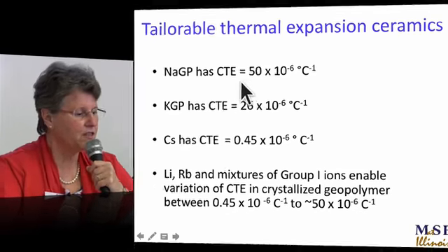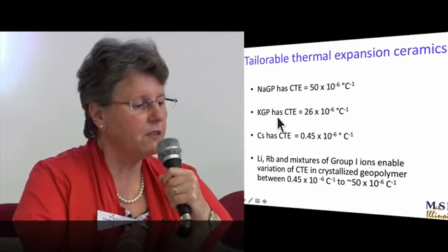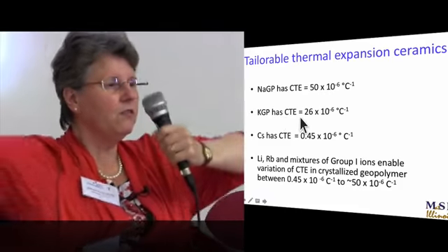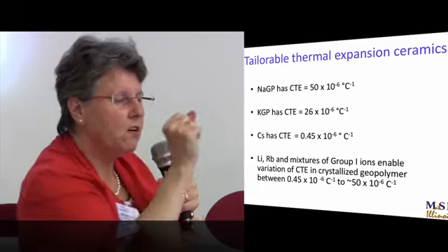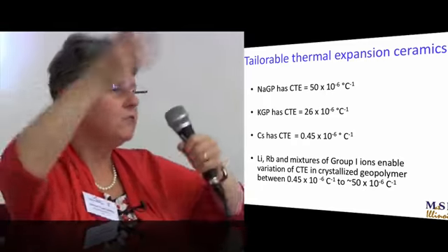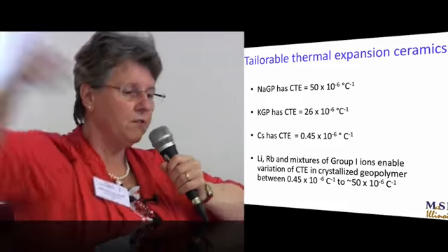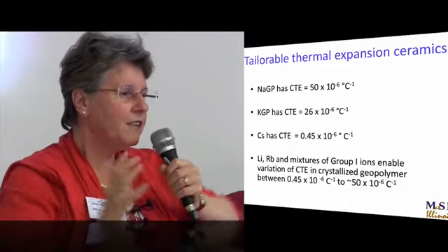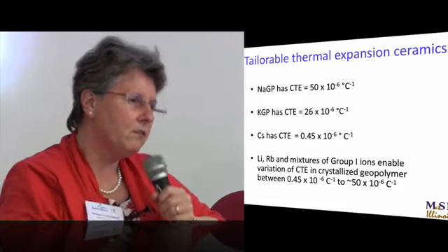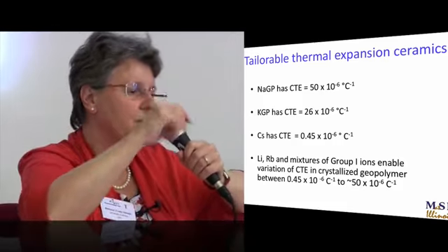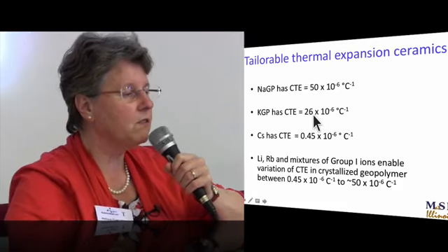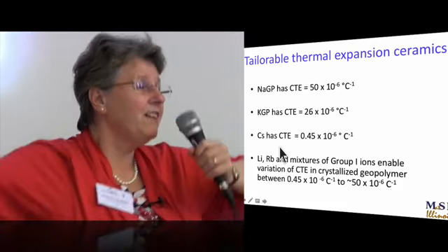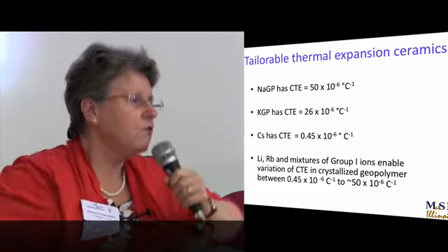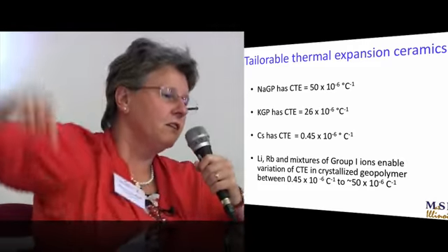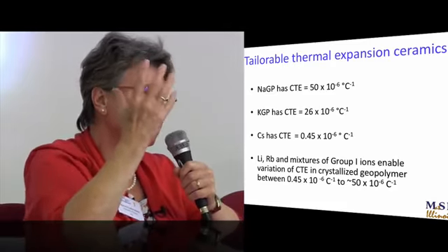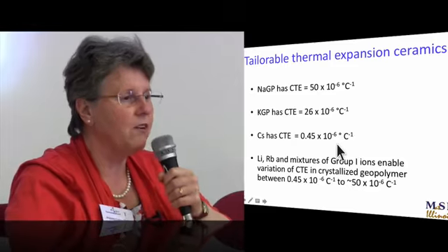So thermal expansions, sodium GP 50 by 10 to the minus 6. That's big long silica chains flopping around a tiny little sodium atom. The chains can do what they like, so they stretch 50 by 10 to the minus 6. Potassium is a bigger cation, so the chains can flop around to some extent, but their thermal expansion is only 26, 28. Cesium is a big fat cation. The sodiums are trying really hard to get around it. So there's very little thermal expansion, 0.45 by 10 to the minus 6.